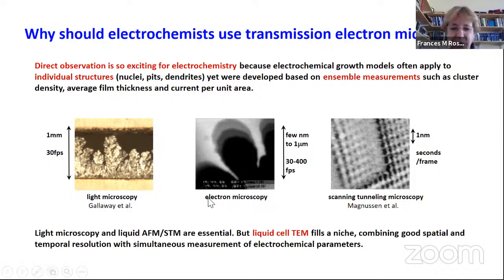And so electron microscopy can occupy a kind of niche where you can record images with a field of view ranging from tens of nanometers to microns. You can record images at hundreds of frames a second, assuming the sample can stand the dose. And so in between these other microscopies, electron microscopy has a real role to play in bridging length scales, and furthermore, linking movies or images of things happening with simultaneous measurement of electrochemical parameters. All right, so that's why we got excited about this.